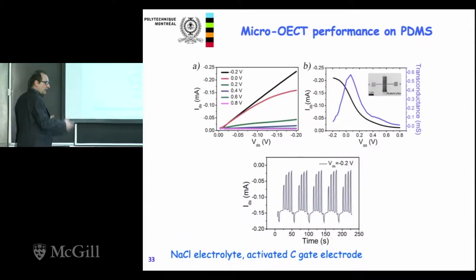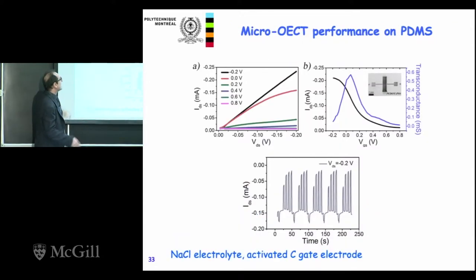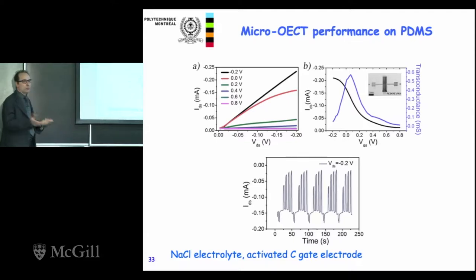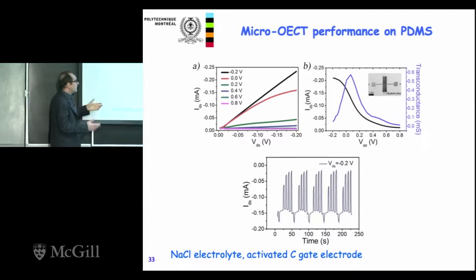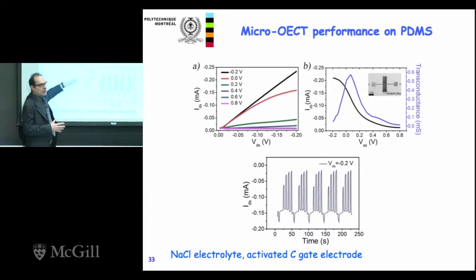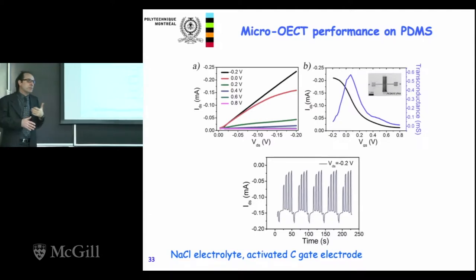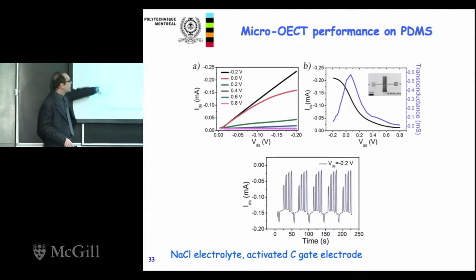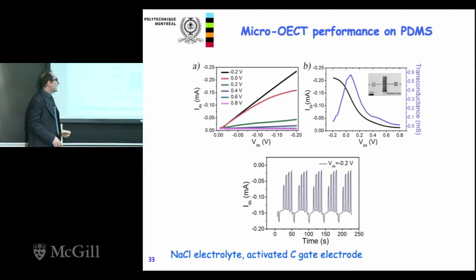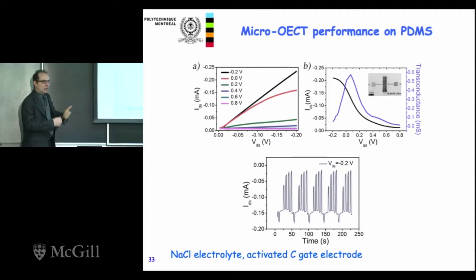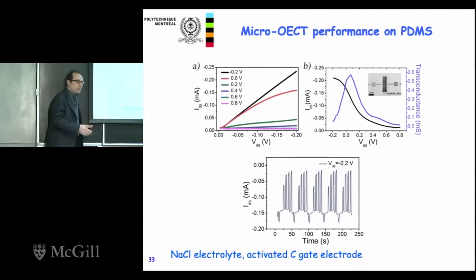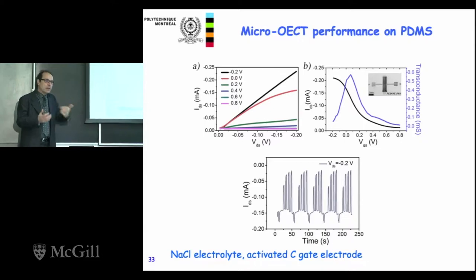Again, we characterize the device electrically. You see the same kind of behavior you observed in the other device. The only difference is that the devices are not as good as they are on PET because PDMS is more problematic as a substrate. Now we know how to circumvent this problem. But anyway, this shows you that each time you have a new process, you have to adapt it to get the maximum you can get.